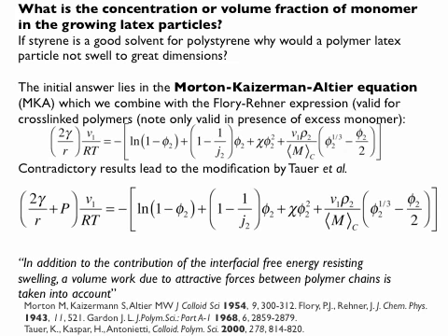That term is the only term that can account for objects that don't mix. And then the last term is almost like a geometric restriction. It's related only to the cross-link density, and it's only important if you use a cross-linking agent. If you don't use a cross-linking agent, Mc goes to infinity, which means that term cancels out. So that's the right-hand side of the equation.